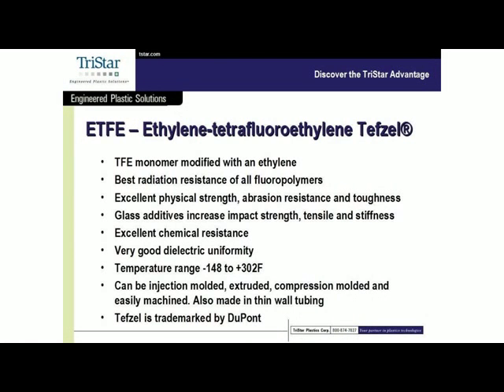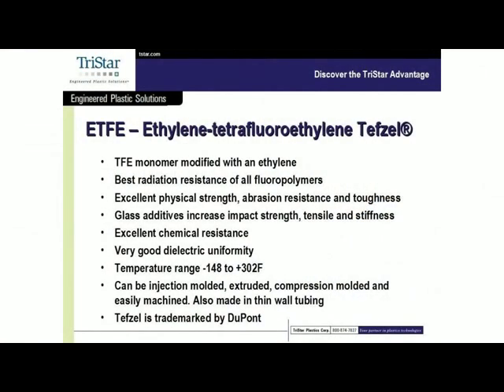ETFE has very good physical strength, has very good abrasion resistance, and it's mechanically a very, very tough material. We can add glass to Tefzel to even increase the strength, increase its stiffness. Like if you wanted to use it for a valve seat on a high-pressure valve. And also its impact strength is dramatically improved by adding glass. It has very good chemical resistance. Temperature range is minus 148 to plus 302. That is the range that we consider continuous. We do have testing that shows what happens beyond 302 degrees Fahrenheit, and while it may still function, there's a dramatic drop-off in physical strength once you pass that point. So our recommendation is 302 at the top end.